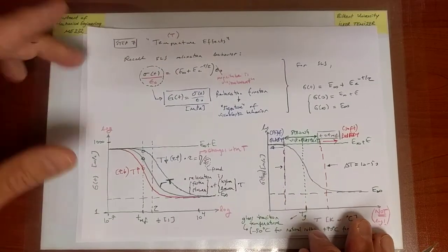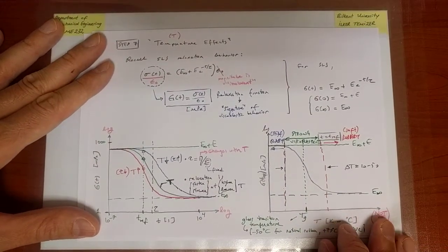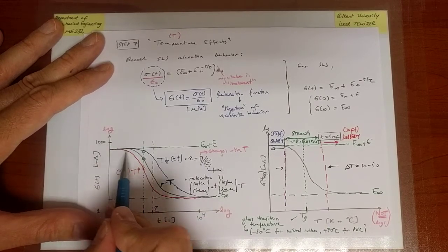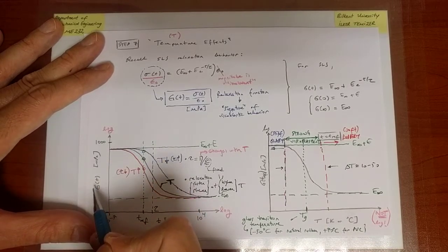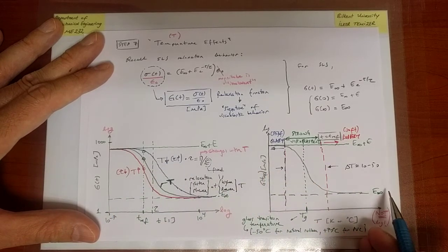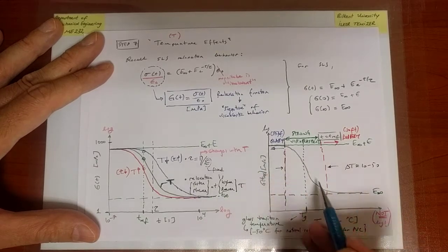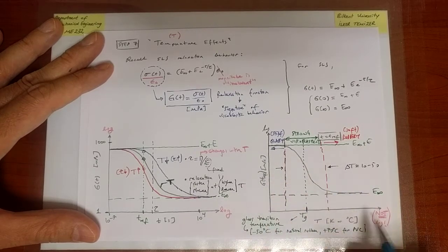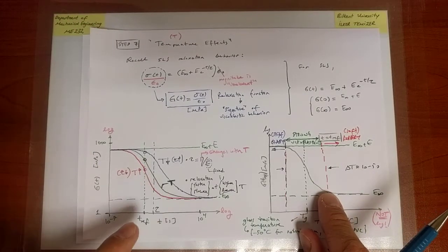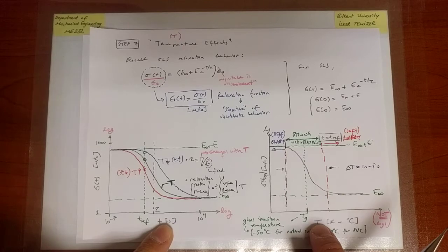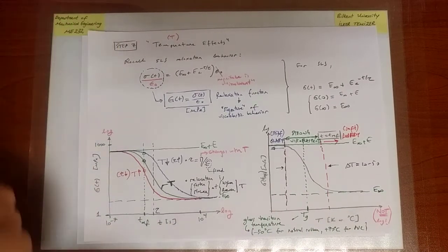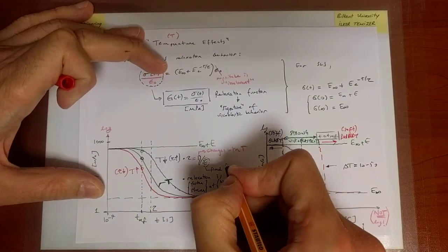What we've observed in the previous slide is that the way the relaxation function varies with time is pictorially the same as the way that relaxation function changes with respect to temperature. So the two pictures are the same. It's just that in one case I have time, in the other I have temperature. This is called the time-temperature equivalence principle.